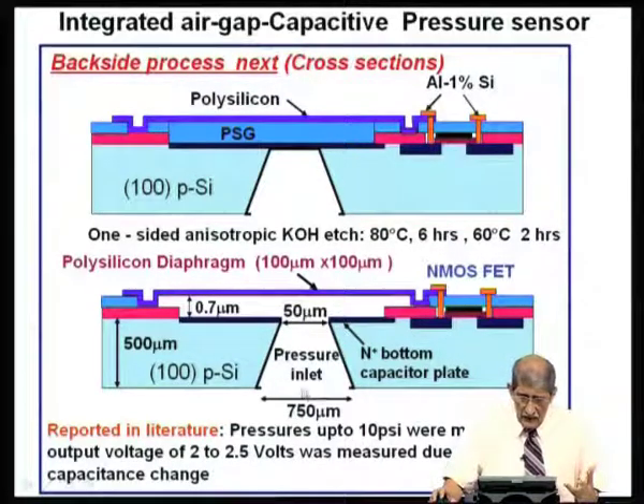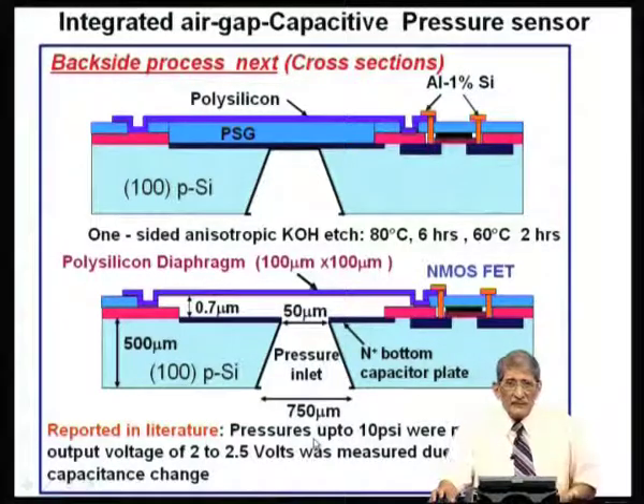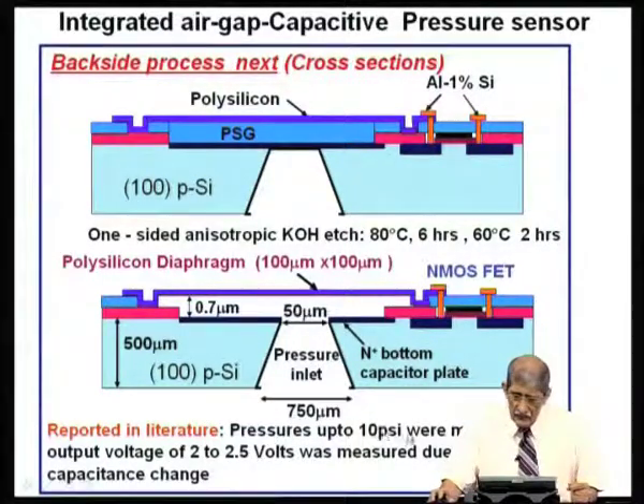Now, the one that is reported in literature for this type of device is actually pressures up to 10 psi were measured, very low pressure. An output voltage of 2 to 2.5 volts was measured due to the capacitance change, and this capacitance change is converted into change in voltage using the electronics.